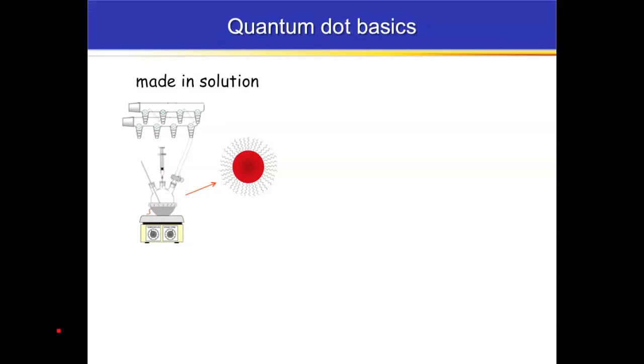Okay, so we make these materials just using normal inorganic chemistry. This is like a Schlenk line kind of setup. The materials come out as a two-component material where you have an inorganic core like lead selenide. I'll mostly talk about lead selenide and lead sulfide today. And then the shell that surrounds the core is a ligand layer that's usually an organic ligand, a long chain material like oleic acid, for example.